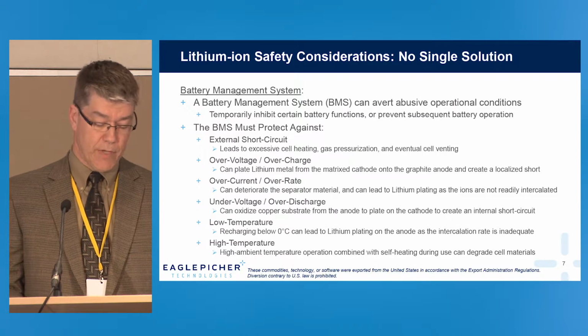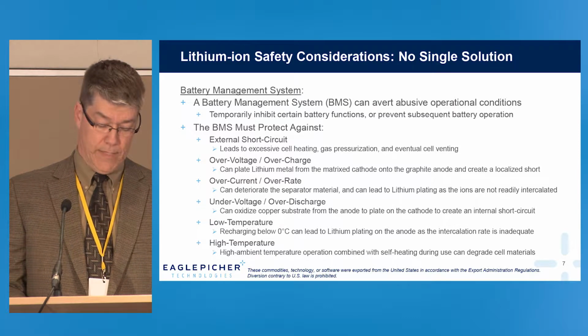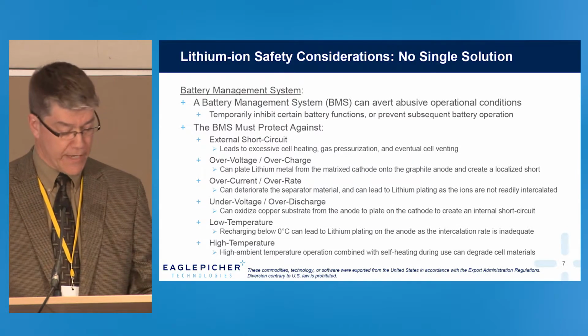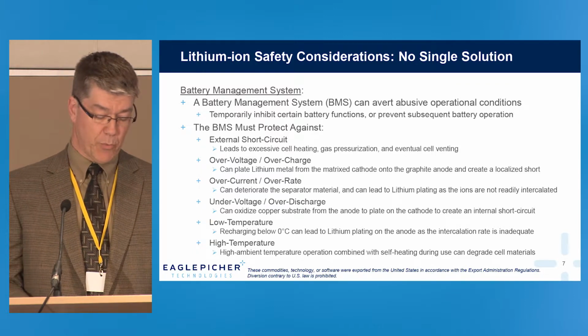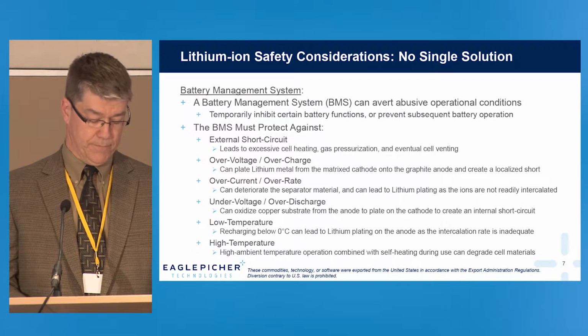Low temperature, recharging when cold. Lithium plating can then result on the anode. And of course, high temperature degrades the cell materials.